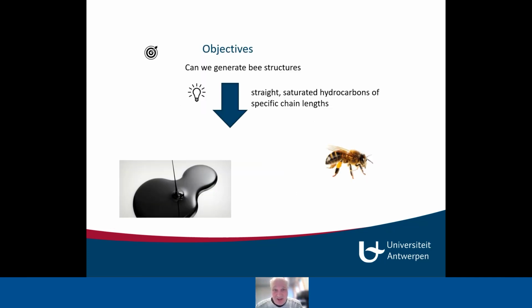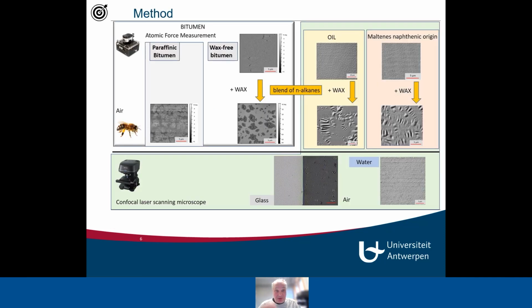The objective, or research question, was: can we generate bee structures? Can we make them ourselves? The idea was, if we take straight saturated hydrocarbons of a certain length, so waxes, and put them in bitumen, can we then get some bee structures at the surface of the bitumen? So we set up a plan and worked with two setups. We used the atomic force microscopy equipment, which we could use from the Vrije Universiteit Brussel. Then we used our confocal laser scanning microscope as an additional tool.